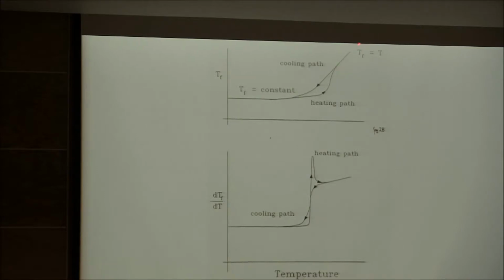When you're at high temperature, you see that there is a one-to-one relationship between the TF, the fictive temperature as we call it, and the actual temperature of the sample. Everything here is very, very simple. It means that when I have a liquid, by definition, its density will be at equilibrium. Its density will be the density it should have at this pressure and at this temperature. It never deviates. That's the definition of a liquid. But if I make the solid at low temperature, then you see that the density doesn't change as a function of temperature. Very bizarre. It actually changes a small amount elastically, but it doesn't change the viscosity. It means that you've frozen the structure. You've locked out the possibility of this glass relaxing right here at the glass transition.